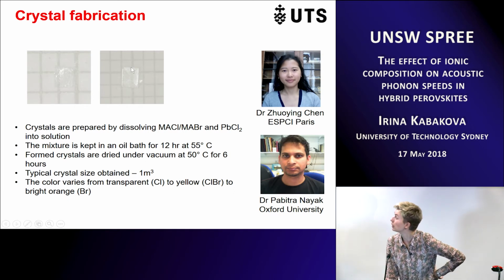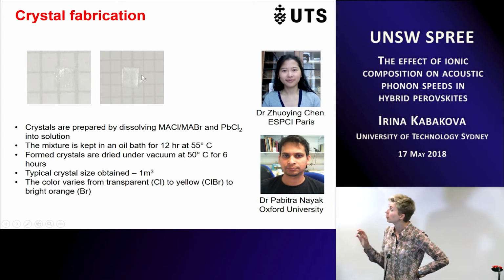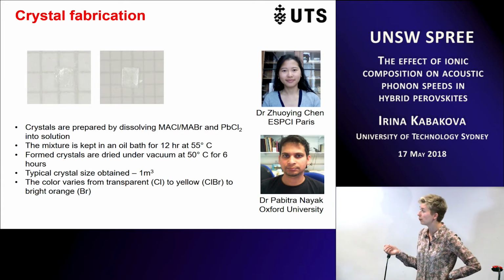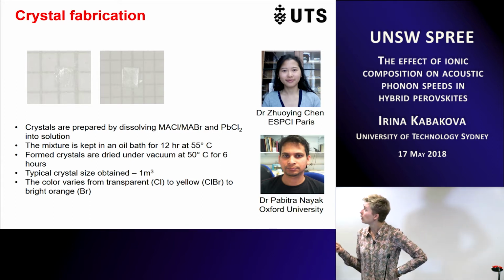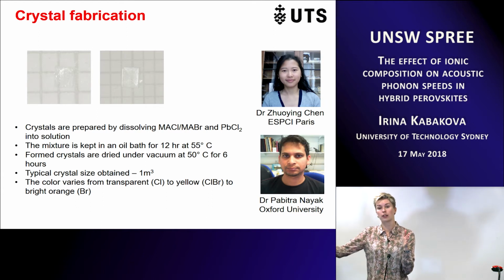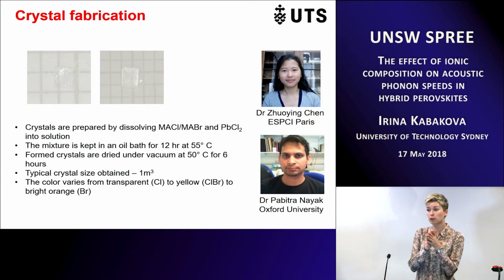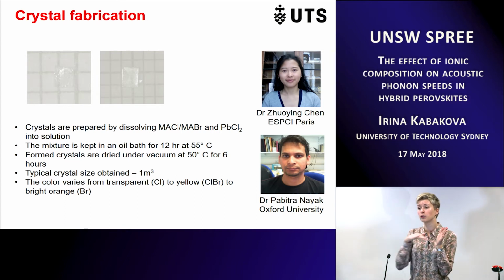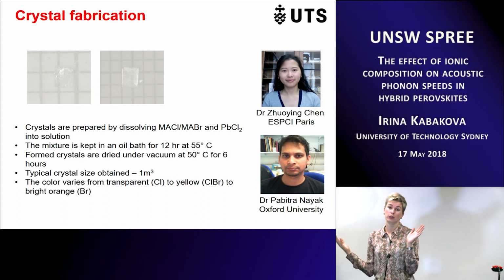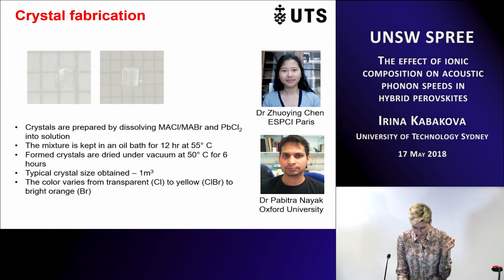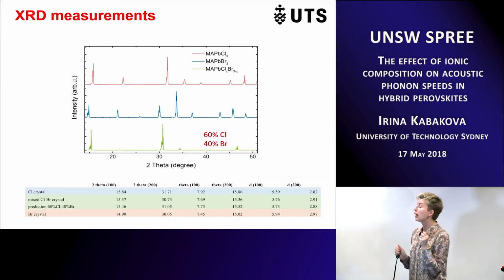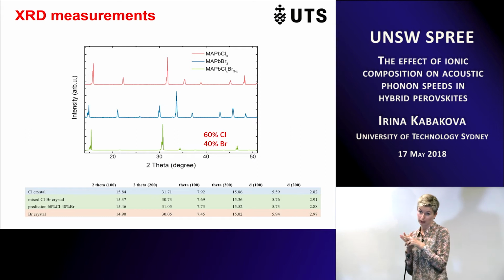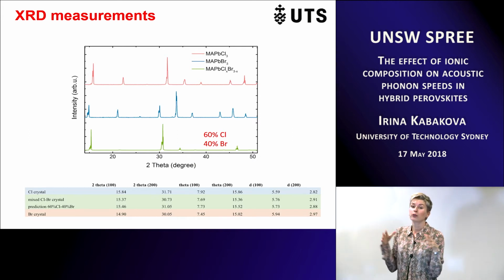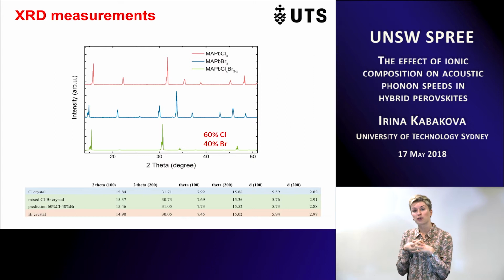They lie here on millimeter-scale paper, and you can see that the lateral dimension is about 1 millimeter, so we can say they're roughly a millimeter cube in volume. Depending on composition, they varied from very faint and transparent for chloride crystals to very bright orange-reddish for bromide crystals. Okay, so we have these mixture crystals, and initially Zhou used a recipe to fabricate